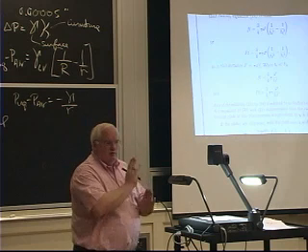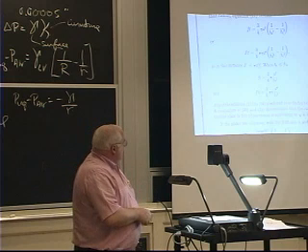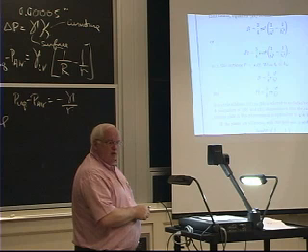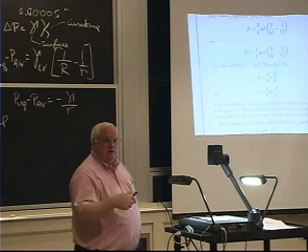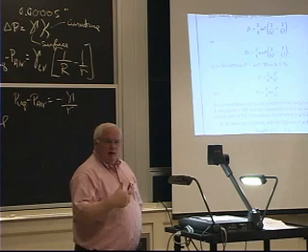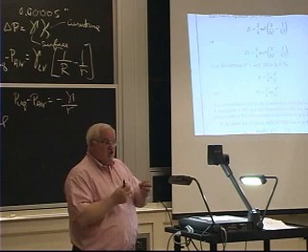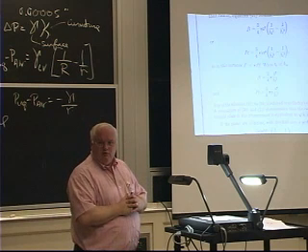Okay, if it's water, but the point here is liquids tend to have this viscosity between 1 and 10 to the 5th. We tend to think of things that are solid as having viscosities that are typically between 10 to the 10th and 10 to the 18th. If you start looking at a solid piece of metal, lead might have a viscosity of 10 to the 14th or something like that.